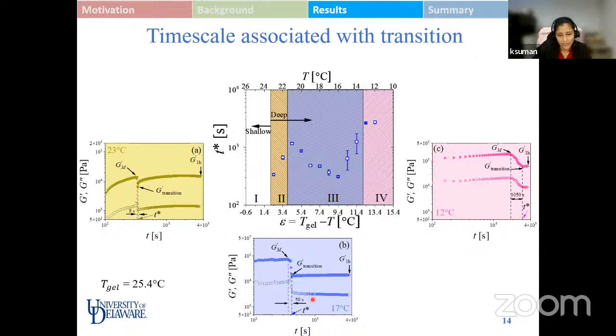So the transition time is quantified in all the temperature aging experiments and is plotted in the center figure over here as a function of extent of gelation. Now the entire domain is bifurcated into 4 regions. The first region is the shallow thermal quench region, where we did not observe any sudden drop in the modulus value, and there was a continuous increase in the modulus value, which is generally observed for polymeric gels or colloidal gels in general. However, we now enter the deep quench region, which is regions 2, 3, and 4 numbered over here. In region 2, we have a drop followed by a continuous increase.